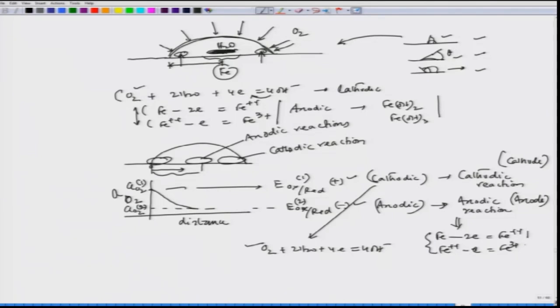So, whenever we have Fe2+ and Fe3+, they would try to form Fe(OH)2 and Fe(OH)3 and they will try to deposit. So, this is the deposit if I consider. So, now corrosion, that means this iron is dissolving. So, the iron is dissolving preferentially in this zone, in the center part, because the center part becomes my anode, and those iron ions will react with the OH minus that is forming in this particular reaction, and they will form a deposit around this zone. So, these are my deposits of ferric oxide, ferric hydroxide or ferrous hydroxide.